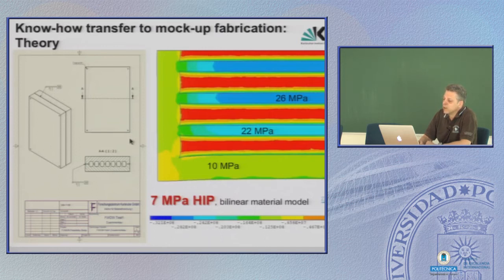And if you load such a plate with a HIP pressure of 7 MPa, you see the real stress throughout the whole plate varies from 10 MPa at the border, and internally at the distance parts between the cooling channels it rises up to 26 MPa. And remember, 26 MPa will produce a creep deformation of more than 5% already.